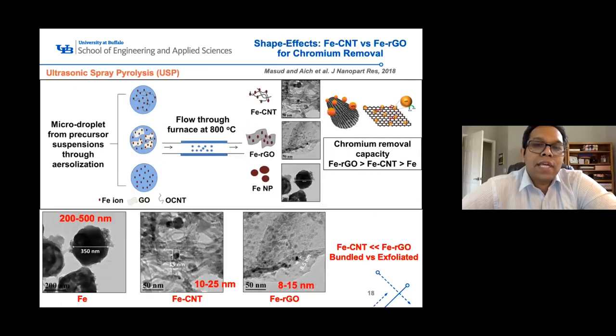So what we tried to see first is, does the one-dimensional or two-dimensional nanomaterial support, which one gives much better performance? So we wanted to make these nanomaterials using an ultrasonic spray pyrolysis process. Here we are using micro droplets, very small droplets of water suspensions with these different types of iron salts, with carbon nanotube, graphene, or without any of the supports. We aerosolize them and flow through a tube furnace at 800 degrees Celsius, and then we get different types of iron carbon nanohybrid. So iron CNT, carbon nanotube, or iron reduced graphene oxide, or just the iron nanoparticles.